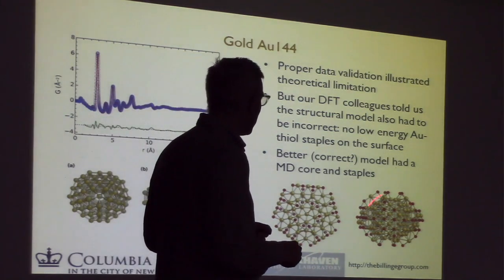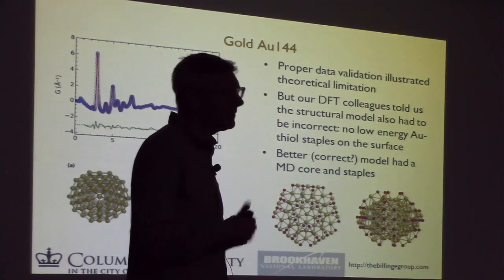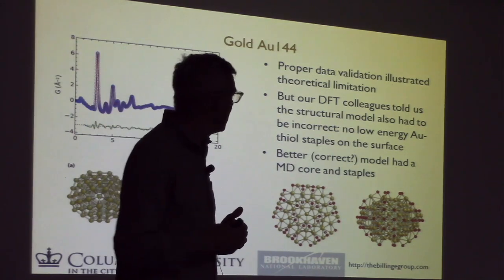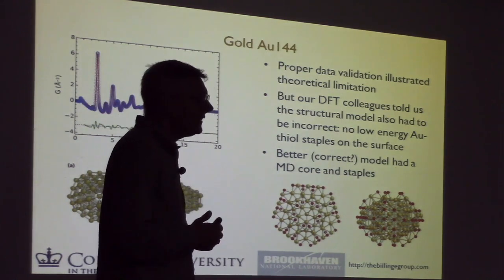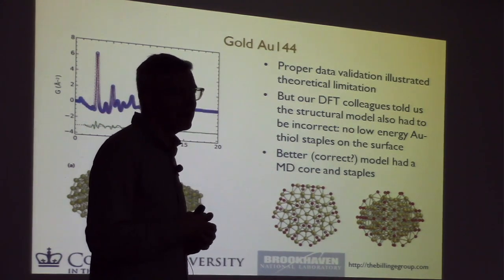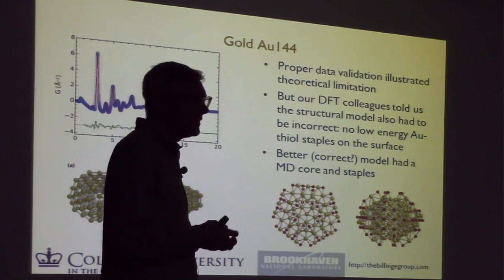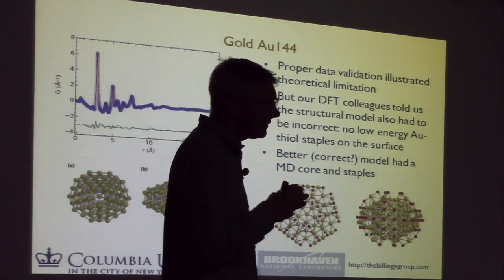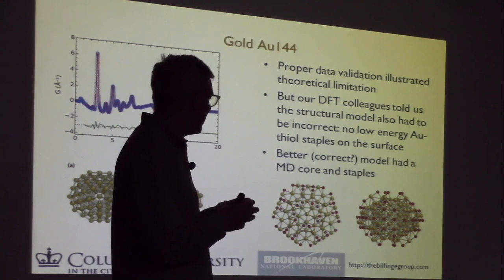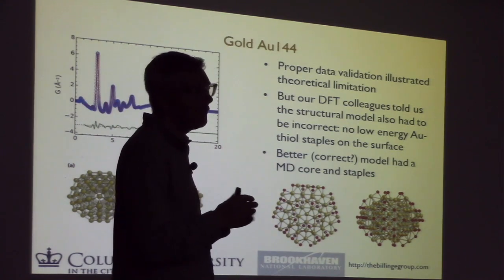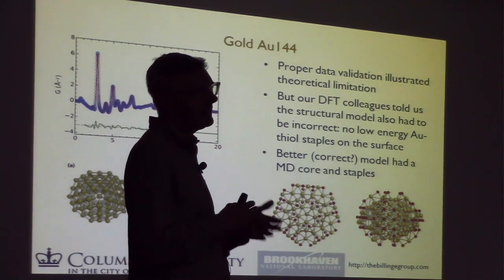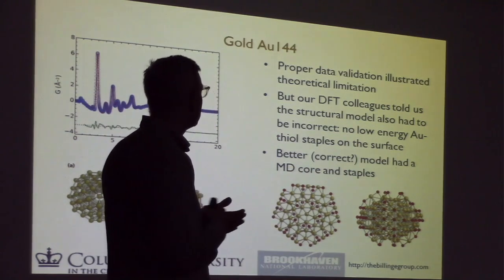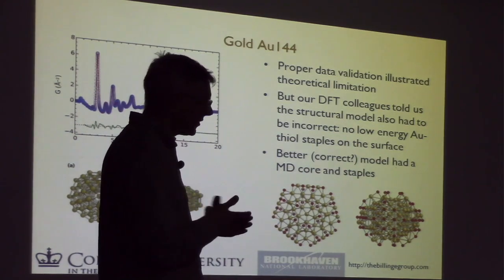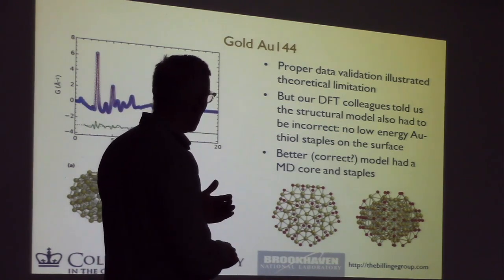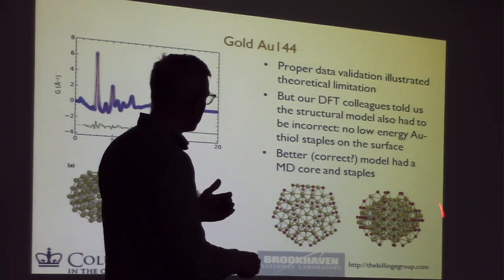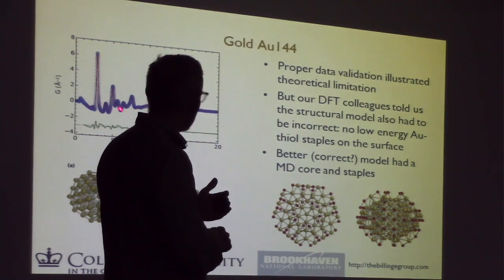So what we did is we went back and we said, okay, it has 144 gold atoms in it. But we need to have 60 of those atoms involved in these thiol staples. So what we did is we made a close-packed decahedral core of 114 atoms. Actually, no, it's 30 golds in the thiol staples. 60 sulfurs, 30 gold. So 114 gold core, and then the other 30 golds we put in staples on the outside, and we also got a good fit.